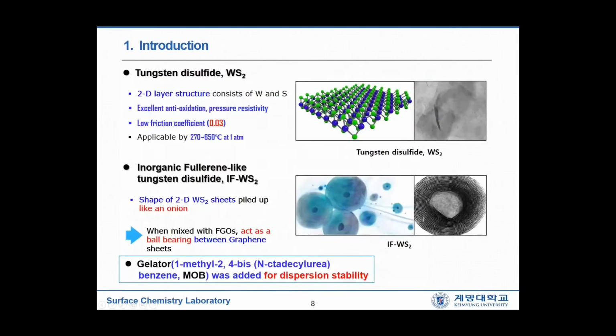This figure shows the structure of tungsten disulfide and inorganic fullerene-like tungsten disulfide. WS2 has a two-dimensional layer structure consisting of tungsten and sulfur. This material shows excellent anti-oxidation property, pressure resistivity, and a low friction coefficient of 0.03. This material is also applicable at 270 to 650 degrees at atmospheric pressure.